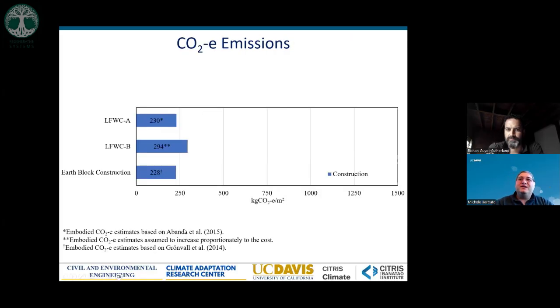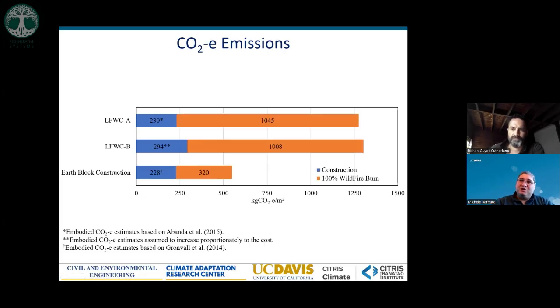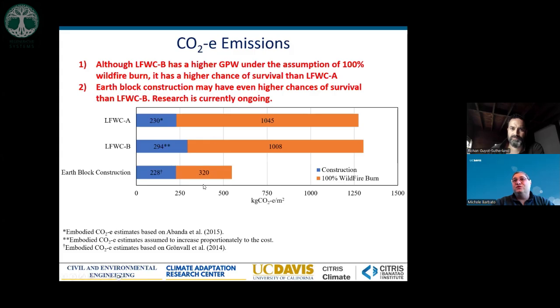So to give it graphically, we took from the literature the estimates in terms of embodied energy from the original construction. And you can see that fundamentally earth block construction is very similar to the wooden construction in terms of the initial embodied energy, which is already a big advantage when compared with the concrete or brick homes, which have an order of magnitude higher in terms of embodied energy. But then when you compare it in terms of total emissions, including the effect of wildfire burn, now you have a total emissions that is significantly lower than the one coming from a wooden construction. It's about a third of it.